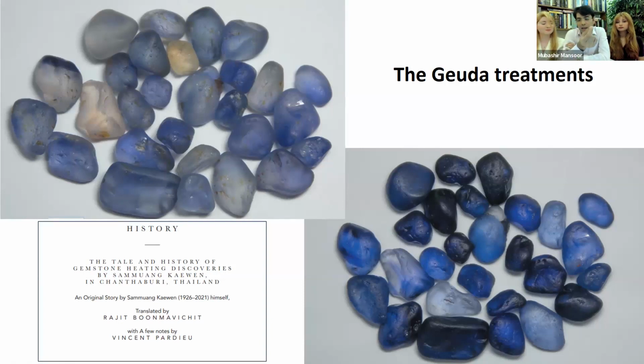We just mentioned the blue color is caused by iron and titanium that are in the structure in place of aluminum in the sapphire crystal. If we dissolve all of those titanium atoms that are positioned in the rutile and we just let them free in the sapphire, then they would now be contributing to the formation of a blue color. And that is a beautiful blue. Absolutely. And it's not only the color that is enhanced, but the clarity as well, because the microcrystals are being dissolved and therefore the clarity increases as well.